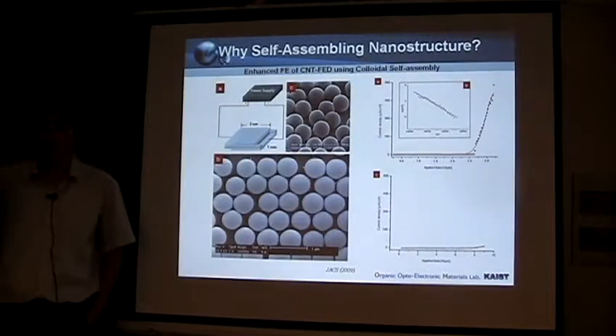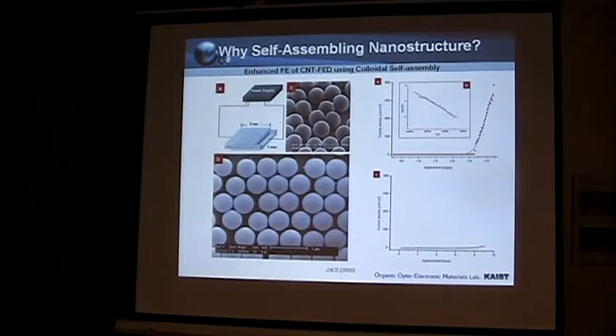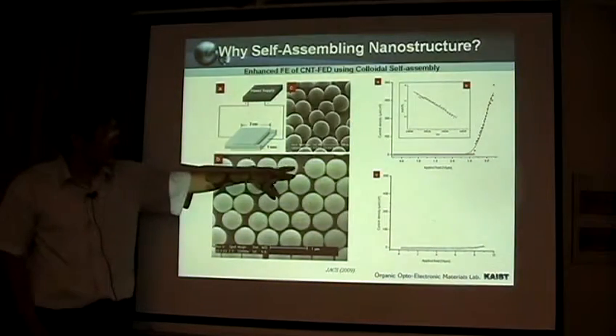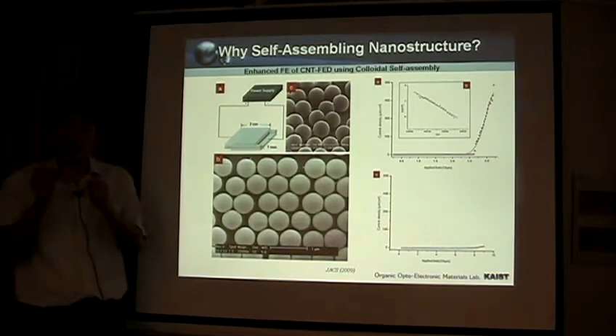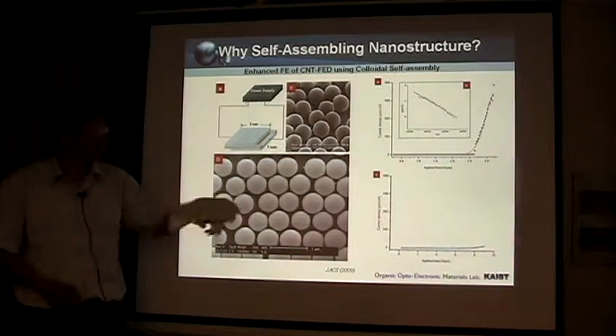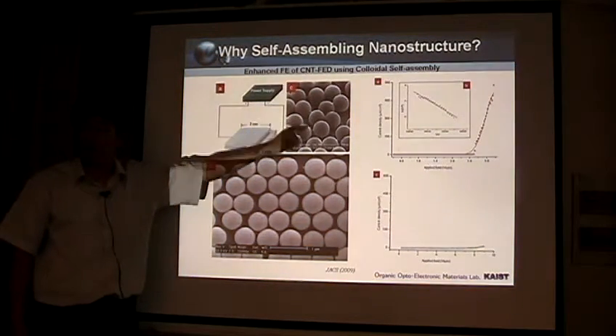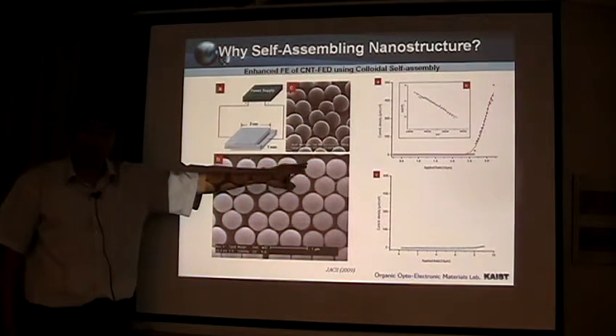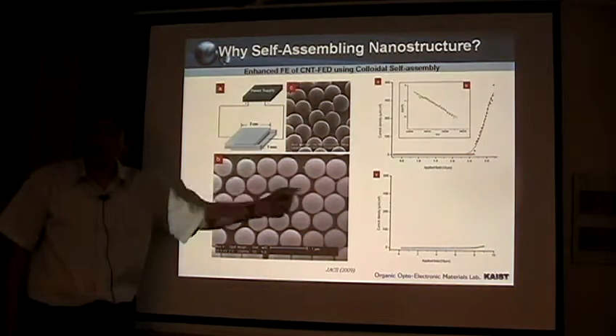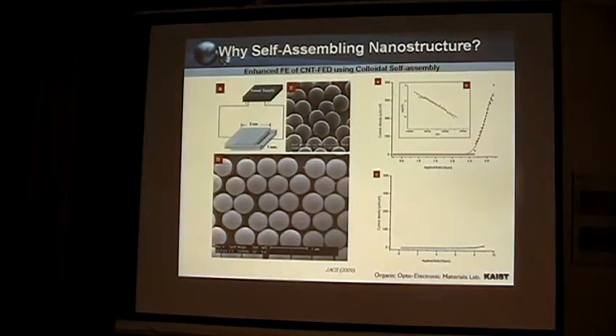Usually in the case of carbon nanotubes, one of the critical issues is the vertical alignment of the carbon nanotubes without any direct growth. There are many ways, but with some self-assembly systems, like colloidal self-assembly, if you deposit some carbon nanotube material, they insert into the intersections within the colloidal self-assembly, cling to the colloids and show alignment. So self-assembly gives alignment of other objects. That's also one of the big purposes of the self-assembly system.